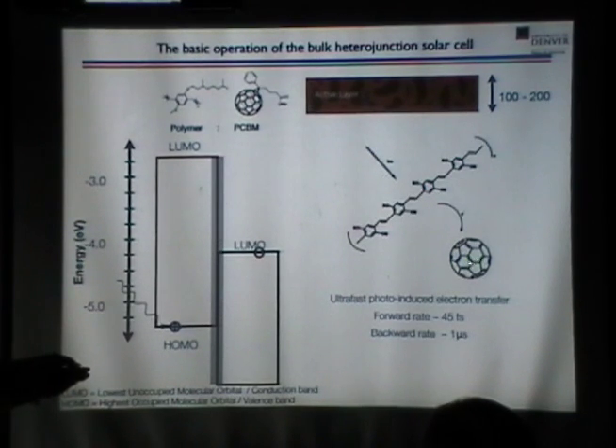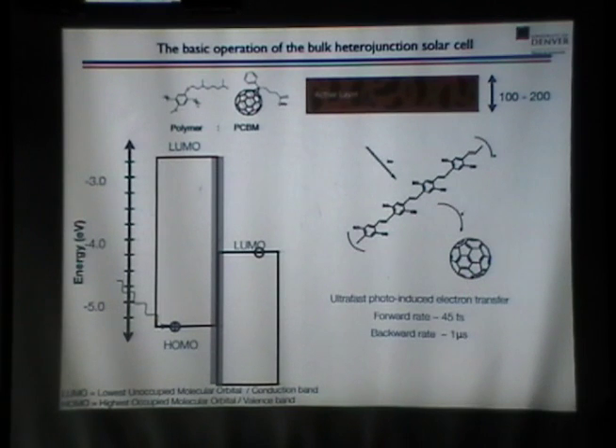So once the electron is on the C60, on the fullerene, the back transfer rate, which would be a recombination process, is much, much slower. This rate is about 1 microsecond. Okay? So you've got 10 to the minus 6 here, you've got about 10 to the minus 14, so you've got 8 orders of magnitude difference in the transfer rates in the forward versus the backwards direction. So that is what really makes possible the operation of the organic solar cell and gives you a very stable charge separated state. That gives you a lot of lifetime for the carriers to migrate out of the device.